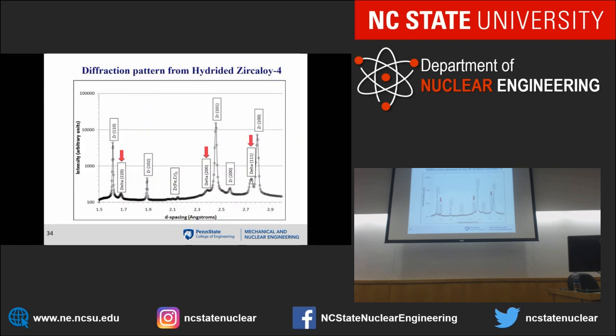And this is what the diffraction pattern looks like. Now, you all know that we have zirconium, chromium, iron precipitates in zircaloy. But it's a very small volume fraction, maybe 0.2, 0.5%. But you can see them pretty clearly here, on a log scale. If this was a lab X-ray machine, this would all be subsumed in the noise. So here we have the Zirc peaks. There are these peaks here, boom, boom, boom. Then we have the precipitate peaks here, and these three peaks shown with the red arrows are the hydride peaks, the delta hydride peaks.